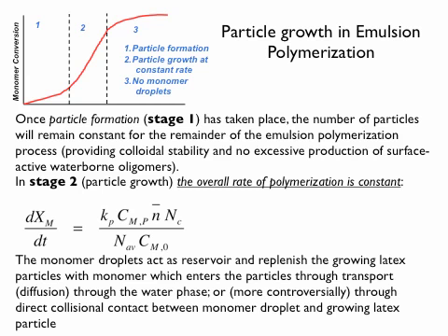And because we have lots and lots of particles, say 10 to the power 16, 10 to the power 20, the average number is a nice number to handle, because if you would do this in moles, you would get weird numbers. We multiply that with the total number of particles per liter, so the average number of radicals times the number of particles per liter.